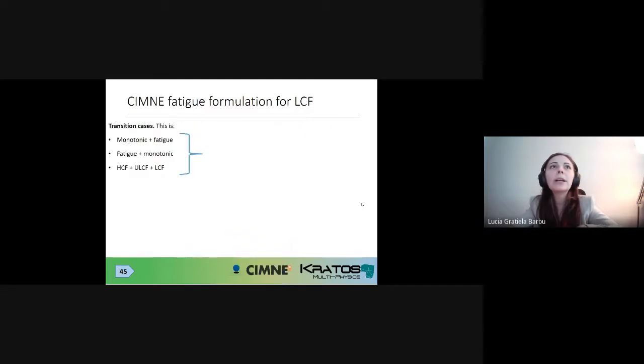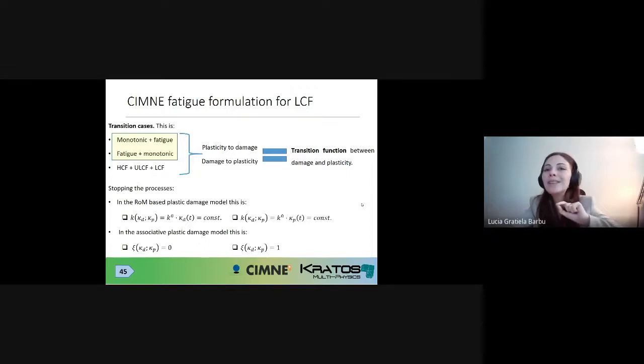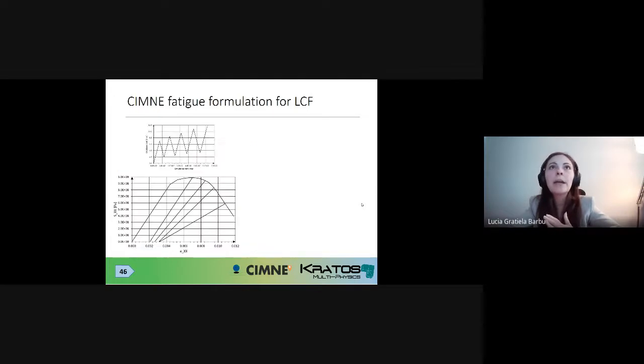I don't want to insist here again, but we also need some transition cases, because as I said, it's important for us to be able to migrate from monotonic to fatigue, fatigue to monotonic, or combinations of cyclic loading. This is why we need transitions from plasticity to damage, damage to plasticity, and we need specific transition functions between these models, just to make sure that we don't recuperate, we don't go back on the level of plastic strain, it's fixed, and we don't go back on the level of damage once we switch from one process to the other.